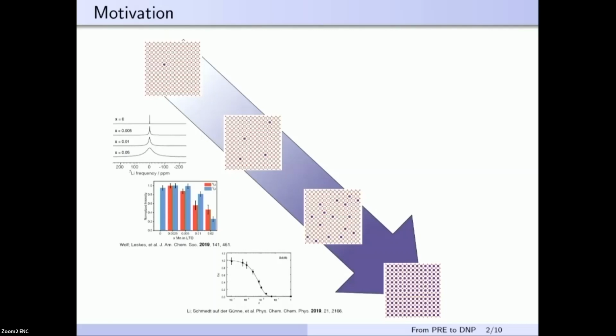And in NMR, we often introduce paramagnetic species to reduce the relaxation times. But sometimes we have to pay a price for this, which is that the lines become broader. And sometimes it even gets to the point that we have signal quenching. By signal quenching, I mean that there will be some portion of these NMR active nuclei that we cannot observe just because of their proximity to the paramagnetic center. This is something that is well known and has been quantified.